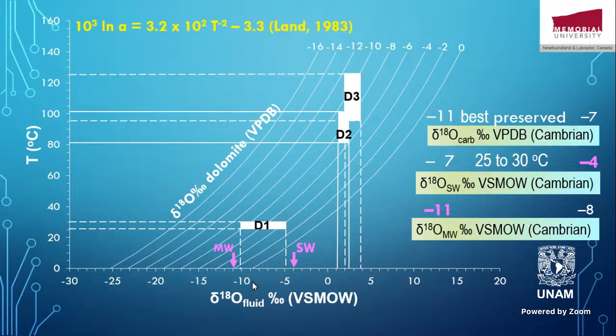Well, can we verify if our assumption is valid or not? Yes, we can. Let's go back to the best preserved delta O18 signature for the middle upper Cambrian, which is probably between -7 and -11. If we apply the same concept that we used for dolomite, but for calcite, there is an equation for calcite by Friedman and O'Neil, 1977. So take the best preserved carbonates during the middle upper Cambrian, from Wenzel in 1999, and look at the fluid or seawater from which they precipitated if the temperature was between 25 and 30 degrees.